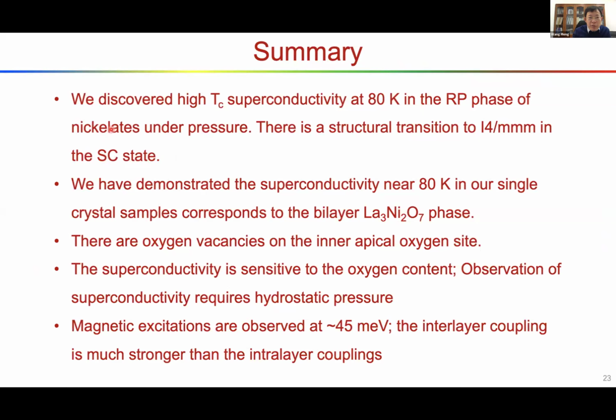Okay, here is a summary of my talk. We discovered high-Tc superconductivity at 80 Kelvin in the RP phase of nickelate under high pressure, and there's a structure transition. We also demonstrated that the superconductivity near 80 Kelvin in our single crystal samples corresponds to the bilayer phase.